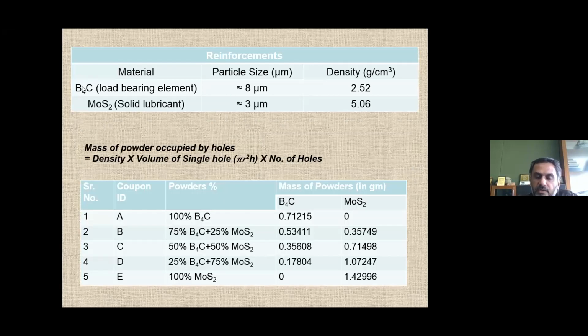One is the boron carbide. You know, in the earlier case, we used to add only the boron carbide. Now we are adding boron carbide plus MoS2 with a certain proportion. So here there is a systematic study which was done in which 100% B4C to 100% MoS2, and with the ratio of 25, 50, 75. That was the ratio which was varied, and the experiments were conducted with the help of the hole method.